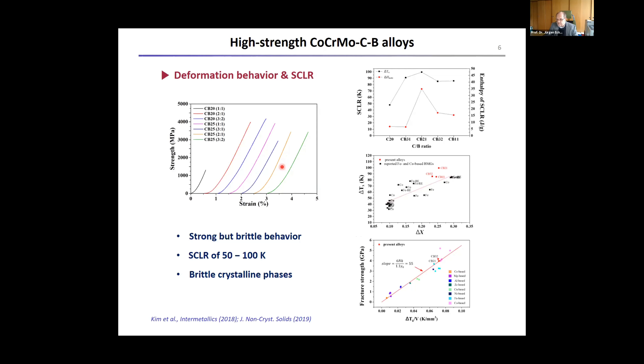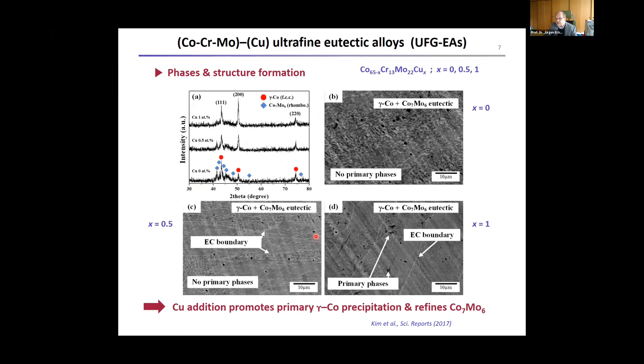You can tune the composition in a different way and go toward a fully crystalline material. Determined by the underlying thermodynamics, you can move away from the fully amorphous structure to something that is a very fine-scale eutectic structure, where you have competing crystalline phases — for instance, a gamma-cobalt FCC structure coexisting with rhombohedral crystals, as seen from the X-ray patterns — with a characteristic eutectic microstructure where these two different phases coexist.